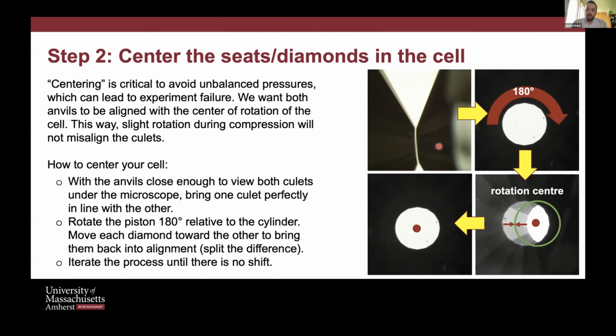When you indent and then you drill and you see that the hole was centered on one side, but it's not on the other side, that means that your diamonds shifted, but they looked good under the microscope. That could be one reason. You might be introducing some rotation as you compress that's causing that problem.